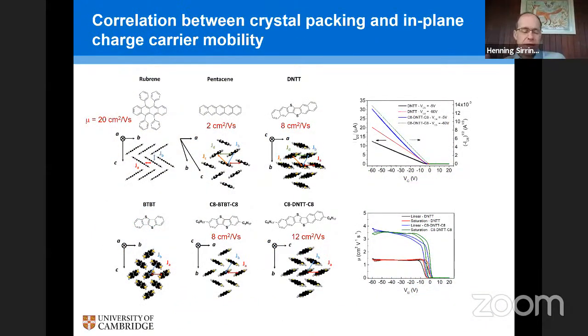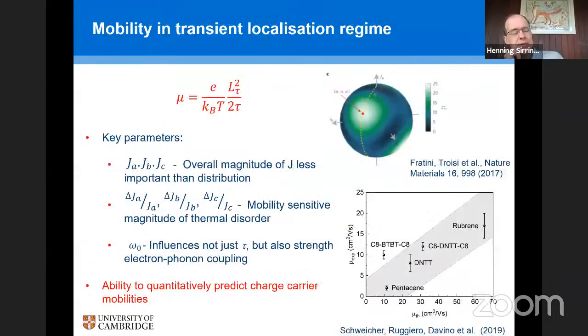And so then, of course, the difficulty is to understand whether this framework is suitable for understanding the differences between molecular systems. I've got here a list of some widely studied molecular semiconductors. As I said, rubrene is one of the highest mobility systems, with mobilities of 20. And then you have a few other systems that have been widely studied because of their high mobilities. And do we have a model that actually explains these differences? And the answer is yes. This transient localization framework is actually able to relatively quantitatively predict mobilities nowadays. You need to take into account a few more details that I haven't spoken about so far.